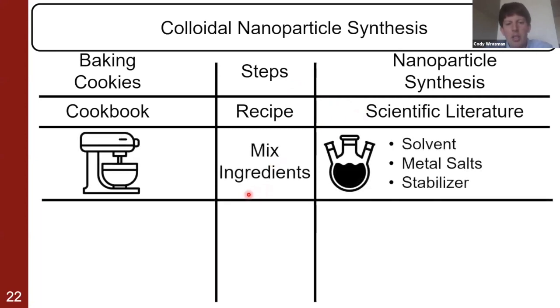You get all of your ingredients and you mix them together. Metal nanoparticles tend to have a few common ingredients. They're a high boiling point solvent, so something that will stay liquid and not boil at temperatures up to 300 degrees Celsius or higher. You need the metal salts that will be those single Legos to make your nanoparticles. And you also need stabilizing molecules that will help keep these nanoparticles from combining back together once you've made them.